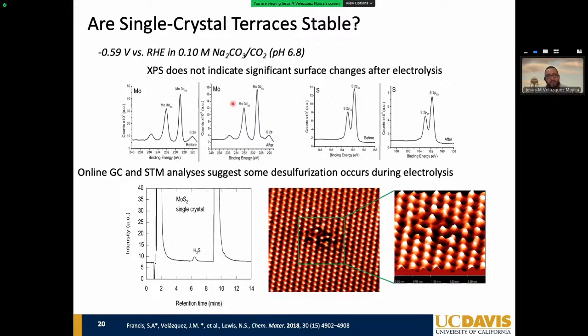However, depending on how much of that little window of the single crystal we exposed, we did see the evolution of an H2S peak under the GC-TCD. And then we further did some high resolution microscopy, and we compared before and after electrochemistry. We saw that at the atomic scale, we're generating more sulfur vacancies. So there is something interesting there in terms of how stable these molybdenum sulfide surfaces are at the applied potentials and the pH in these conditions when we're doing CO2 reduction.